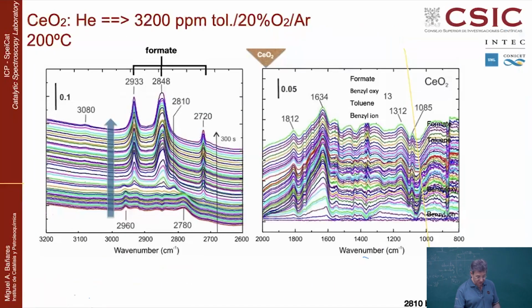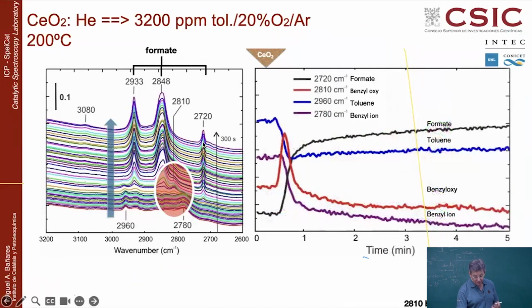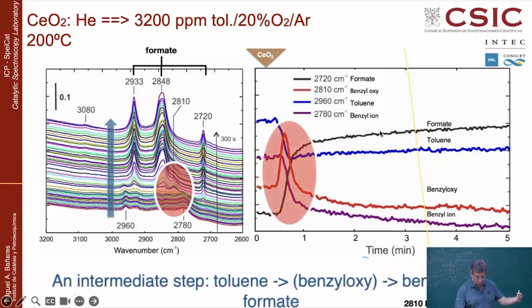Well, in the presence of oxygen, what happens is like a ceria catalyst, for instance, you flow through it and you see something. You see like there is an absorption here that goes into another intermediate and then goes into that one. And you see the development of other bands here. So if you integrate the bands, basically what you observe is that the toluene within a minute starts to be consumed. Within the minute, you start to see like benzyloxy, which is this alkoxide that is being formed and then goes through a maximum and disappears because you start to get the formation of formate species. So you are starting to oxidize the material.